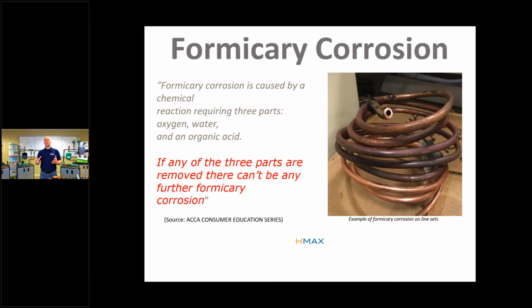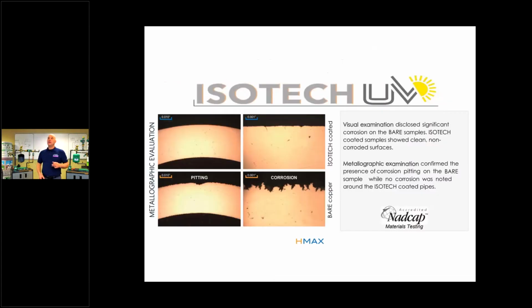So formicary corrosion is basically a combination of moisture and some VOC, volatile organic chemical. And what happens is that moisture mixes with this volatile organic chemical, and it can create a slight acid. So it starts to corrode the copper. And this is from a metallurgist. What it does is it corrodes and pits the copper until it eats its way through and creates a leak.